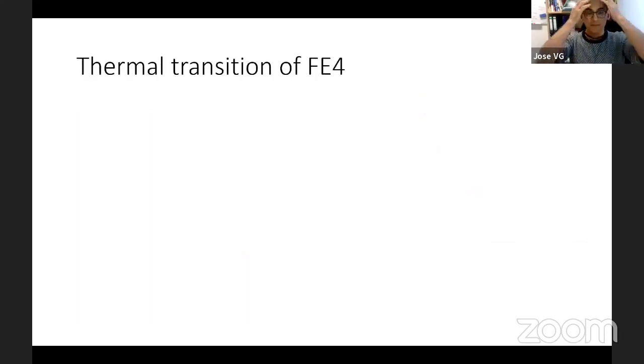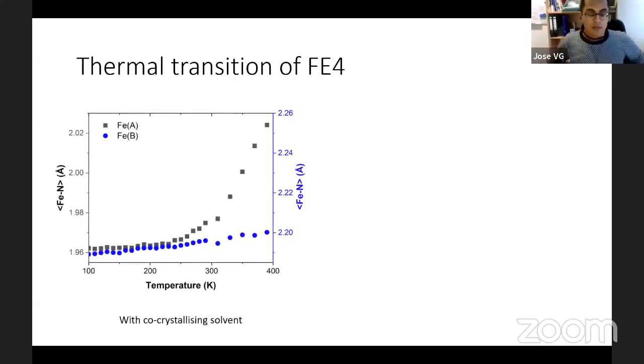There is also more work I still need to finish for the iron 4 grid. The iron 4 grid, all the grids, have co-crystallizing solvent. However, there is something funny about the iron 4. So, for example, here, we can see the bond length expansion with temperature of the iron 4. When we increase the temperature from 100 to 400, we can see a bond length expansion, not a linear bond length expansion, from